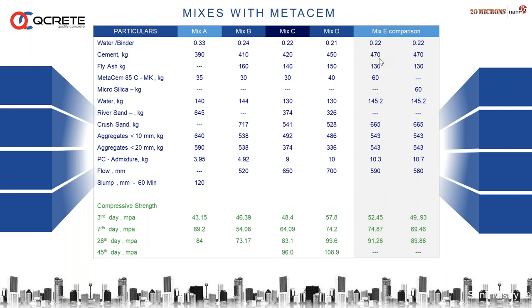That the cement here we kept at 470 and 130 kg of fly ash, and we used 60 kg of Metakaolin, a little bit on a higher side. It was designed using crusher sand here, and the flow of 550-590 is achievable. You can see the difference, like the consumption of admixture is also a little bit